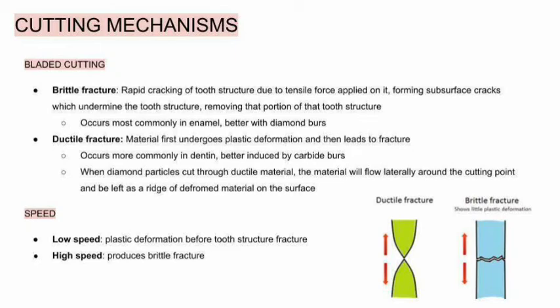In ductile fracture, on the other hand, the material first undergoes plastic deformation and then leads to fracture. It occurs more commonly in dentine and is better produced by carbide burrs. When diamond particles cut through ductile material, such as dentine, the material flows laterally around the cutting point and will be left as a ridge of deformed material on the surface. Thus, carbide burrs are preferred for cutting dentine and diamond burrs are preferred for cutting enamel. Speed is another factor that comes into play here. For low speed cutting, plastic deformation occurs before tooth structure fracture, while high speed cutting produces brittle fracture.